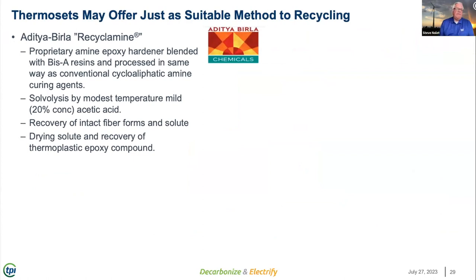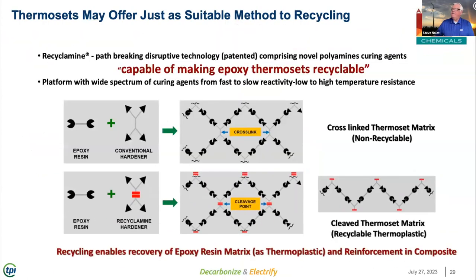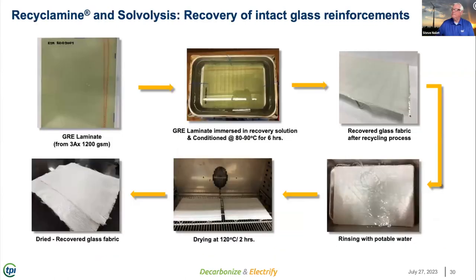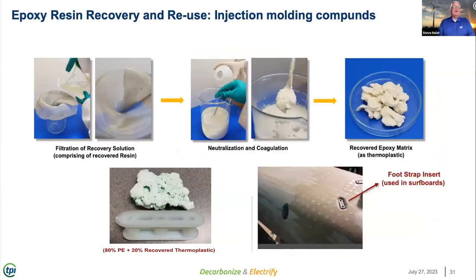Similarly, you might be familiar with Recyclamine, which is a cycloaliphatic amine, but the hook with the cycloaliphatic amines is we can build an internal cleave point within that cross-link network. And with very mild solutions, we can break that cleave and dissolve the resin. In fact, in this simple demonstration, a glass epoxy laminate is dissolved in an acetic acid bath that's 20% concentration vinegar for about 6 hours at 80 degrees C. Low energy, mild caustic solution, recovered fiberglass, and a solute that is now a thermoplastic epoxy that can be ground, compounded, and put into new applications.